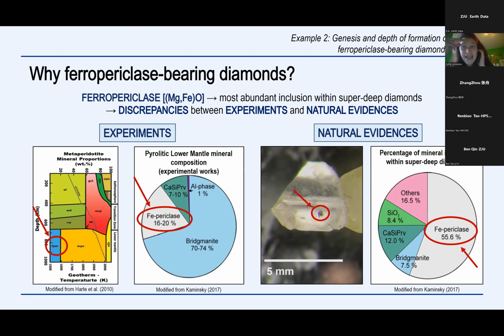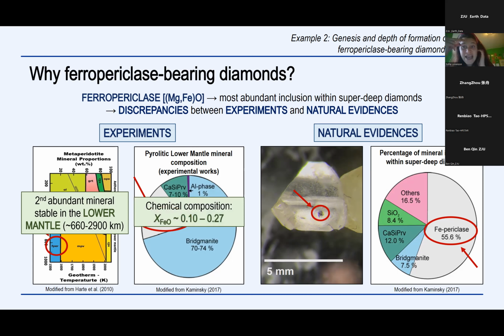In fact, if we consider the experiments, starting from a pyrolytic bulk composition of the Earth, ferropericlase results the second most abundant mineral phase stable in the lower mantle at depths between about 660 and 2,900 kilometers. And this mineral is in association with bridgemanite and calcium perovskite. The chemical composition of this ferropericlase would be magnesium rich, having values of iron index between about 0.10 and 0.27. On the other hand, from the study of natural inclusions within diamonds, ferropericlase results the most abundant mineral inclusion within super deep diamonds, representing about 56% of total inclusions.